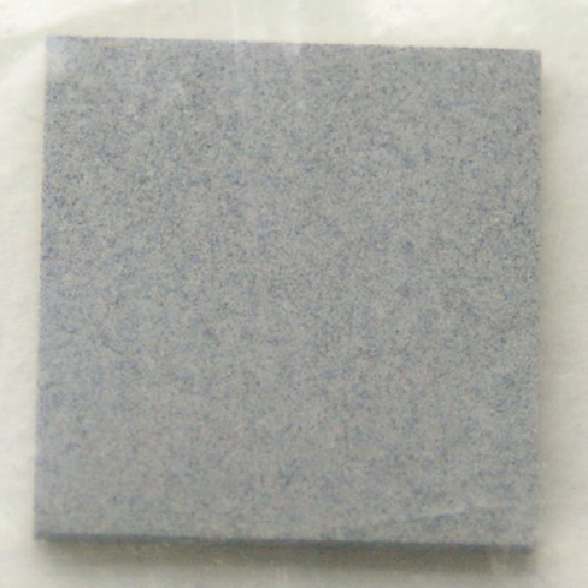Processing. Silicon nitride is difficult to produce as a bulk material. It cannot be heated over 1850 degrees Celsius, which is well below its melting point, due to dissociation to silicon and nitrogen. Therefore, application of conventional hot press sintering techniques is problematic.